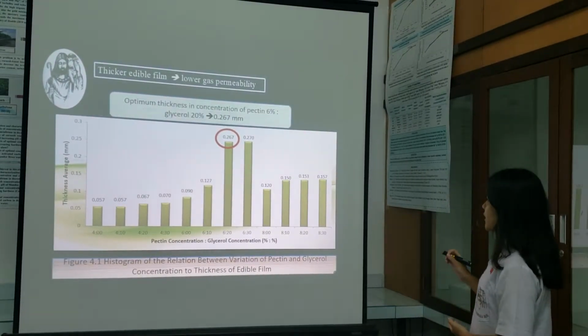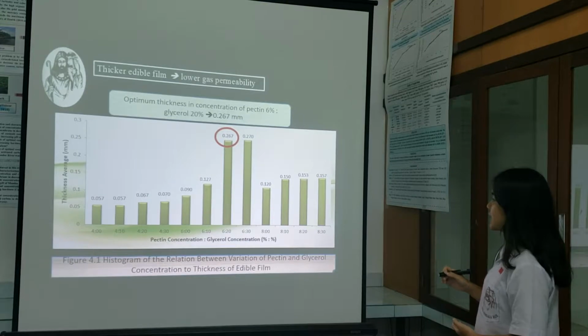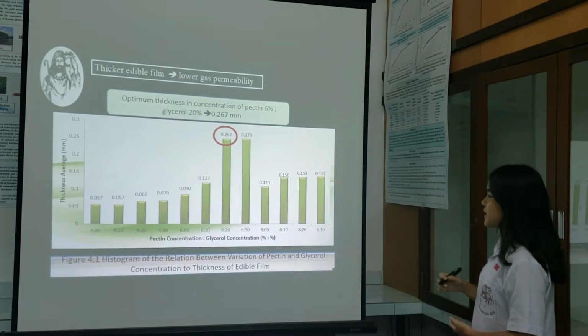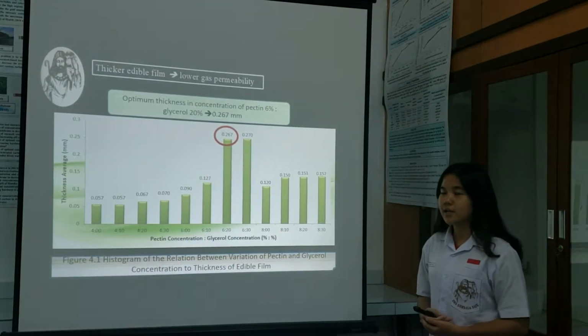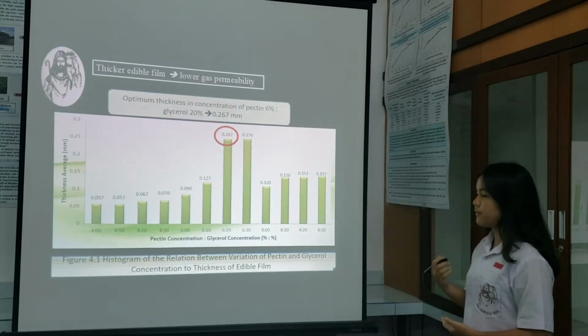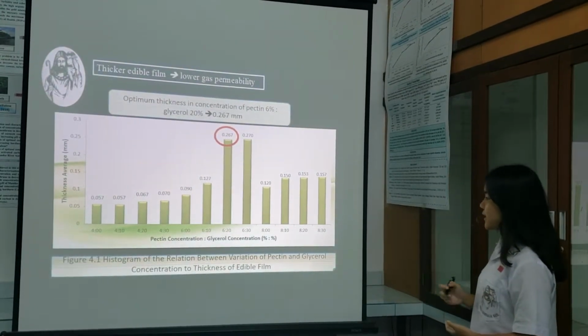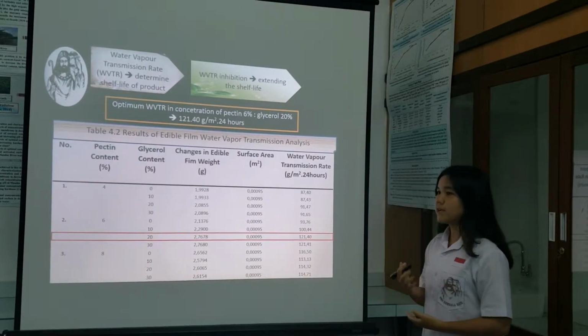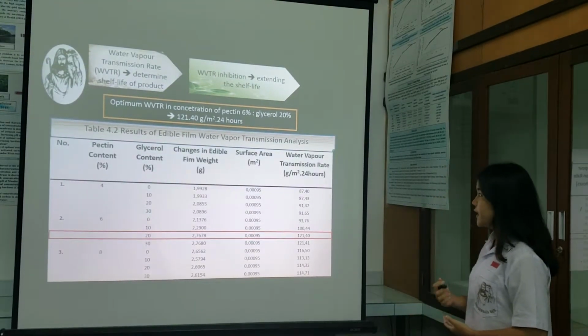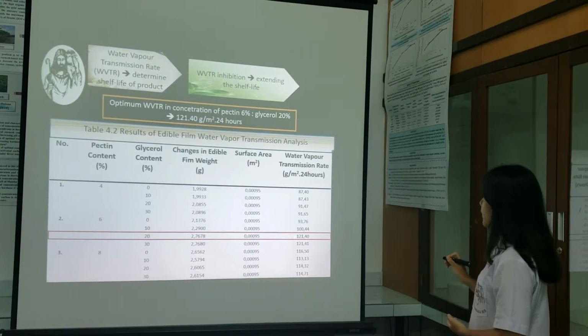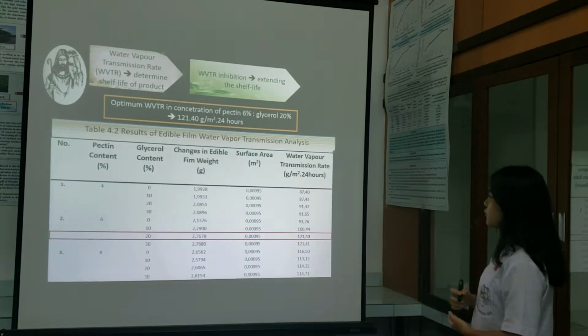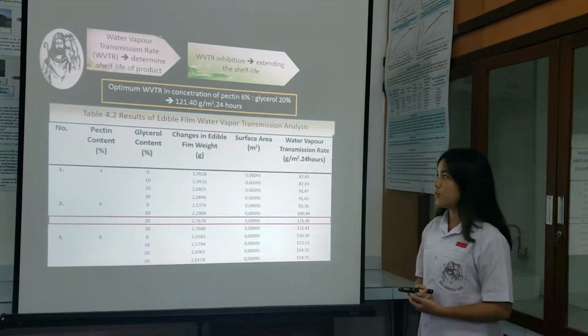We can see that the variation of 6% pectin, 20% glycerol and 6% pectin, 30% glycerol are not significantly different, so it can be concluded that the optimum variation is 6% pectin, 20% glycerol. From the following table, we can see that the optimal variation produces the water vapor transmission rate of 121.4 gram per meter square times 24 hours.